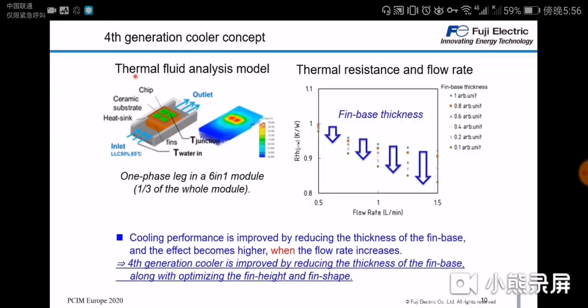Here we can see a thermal fluid analysis of our 4th generation cooler structure. On the left side you can see a schematic of our cooler with the bottom base plate, then in blue arrows showing the water inlet and water outlet. Then we have the fin structure shown in this copper color block here. On top there is the fin base, which is semi-transparent here in this graph. On top of this fin base we have the ceramic substrate and the chips. The thermal resistance is of course measured from the junction temperature of the chips to the water inlet temperature.